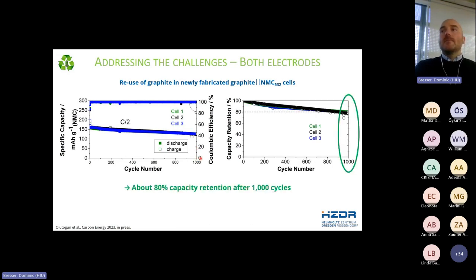You can see here, after 1,000 cycles, we have about 80% capacity retention, which is usually considered the end-of-life criterion. So that's at least comparable, in fact, with the performance of what we got for pristine graphite materials, depending on the supplier, I may say. So the recycled graphite was clearly better than some, very comparable with others, and maybe a little less performant with a few, let's say, high performance graphites.